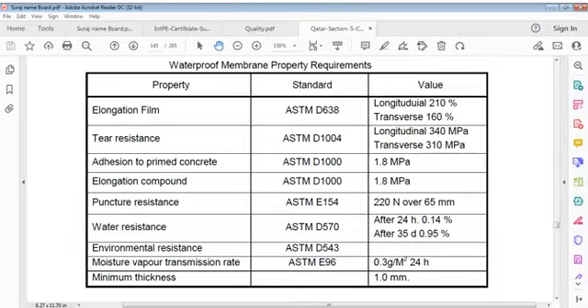Environmental resistance, ASTM D543, not given. Moisture vapor transmission rate, ASTM E96, is 0.3 gram per square meter per 24 hours. Only 0.3 gram. It's negligible. Water resistance is 0.14%, I don't know what that is. Likewise, we can say minimum thickness is 1 mm.